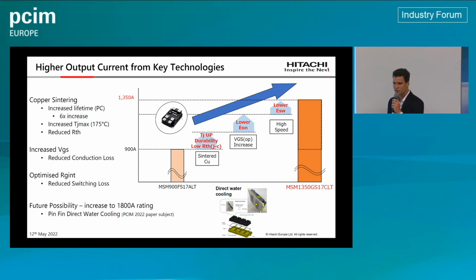So we've got a few different technologies applied, and all of this is benchmarked against our mass production module, which is a 900 amp, 1700 volt full silicon carbide MOSFET in our NHPD2 package. This is the new high power density dual, targeting high power applications in a 140 by 190 millimeter package. Benchmarking that technology, we apply three key technologies. Replacing the die attach from solder to copper sintering gives us substantial increases in power cycle and thermal cycle lifetime, in the order of maybe 20, 25 times increase. It says 6 here, but new testing is still ongoing because we haven't yet broken it.